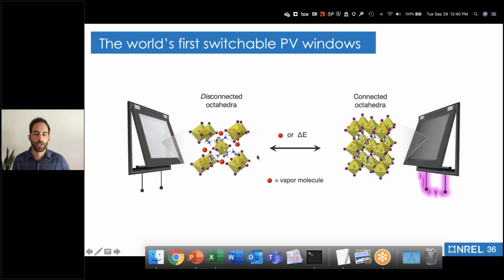On the left side, if you wanted to bleach it, all you need to do is basically take those octahedra and spread them out a bit. When you do that, the material's properties change enough that you get essentially no absorption in the visible. And so you can reversibly do this because the formation energy is so low with different vapor molecules. We do this with methylamine to start with, and now we're doing it with water and things like methanol. So very non-toxic and ubiquitous materials. We can basically intercalate in and out, just like a battery or an electrochromic, to change the color of this material over and over again to make a switchable photovoltaic window.